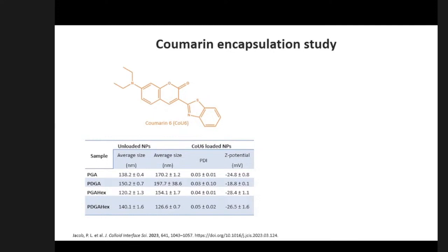Their ability to encapsulate hydrophobic molecules was evaluated by the co-nanoprecipitation method of polymer with coumarin-6, used as a model drug. And after the encapsulation, sizes were generally higher than before, and the zeta potential was still negative.